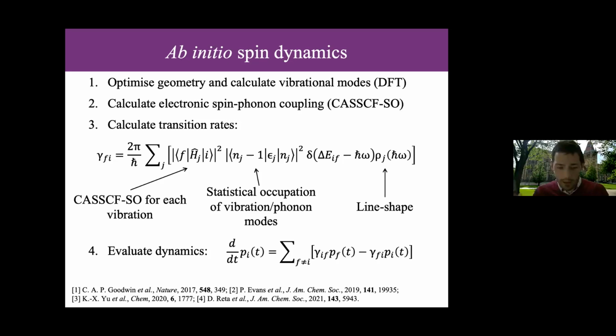And the general approach, and all of these groups take subtly different flavors to this, but we usually start by taking a computational approach to optimizing molecular geometry, whether that's in a crystalline phase or a gas phase, and calculating vibrational modes. And that's usually done with density functional theory. And so here is a first step where we are making already the assumption that we have a weak coupling between vibrations and electronic degrees of freedom, because we are saying inherently by using a density functional theory method here that we are using the Born-Oppenheimer approximation. Now, you don't have to, but that is the most common implementation. So in our calculations here, I'll talk about we are using gas phase optimization. So there is another layer of approximation, right?